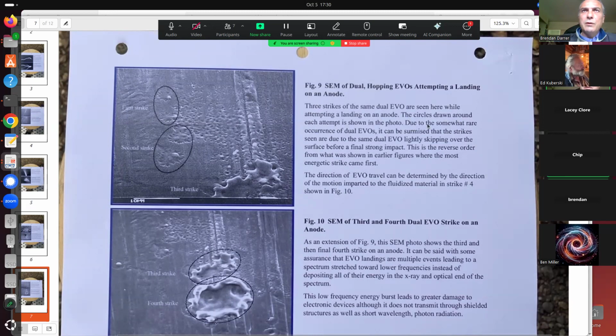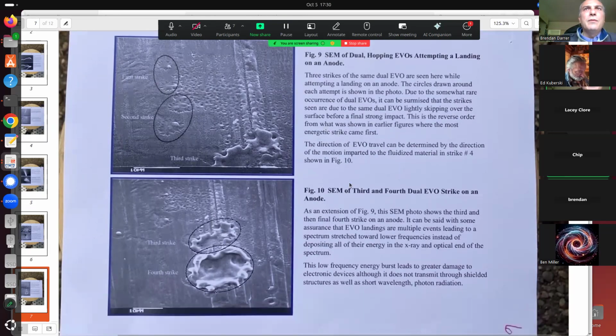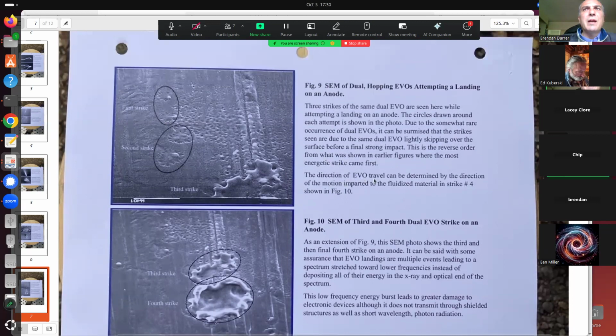Due to the somewhat rare occurrence of dual EVOs, it can be surmised that the strikes seen are due to the same dual EVO lightly skipping over the surface before a final strong impact. This is the reverse order from what was shown in earlier figures, where the most energetic strike came first. The direction of an EVO travel can be determined by the direction of the motion imparted to the fluidized material in strike number 4, shown in figure 10.